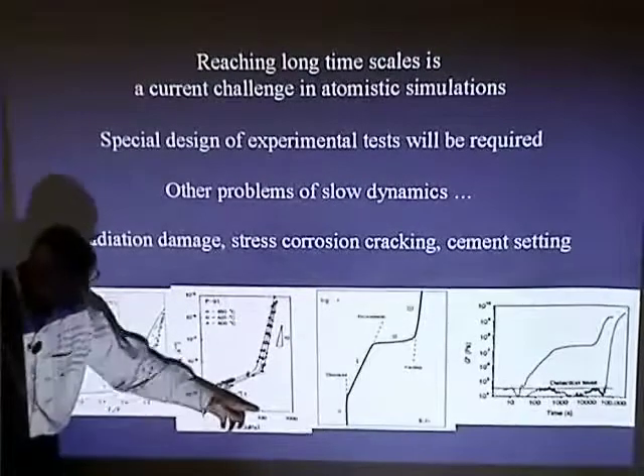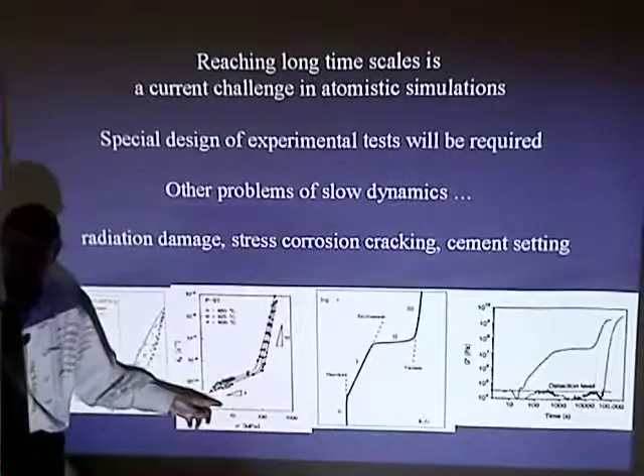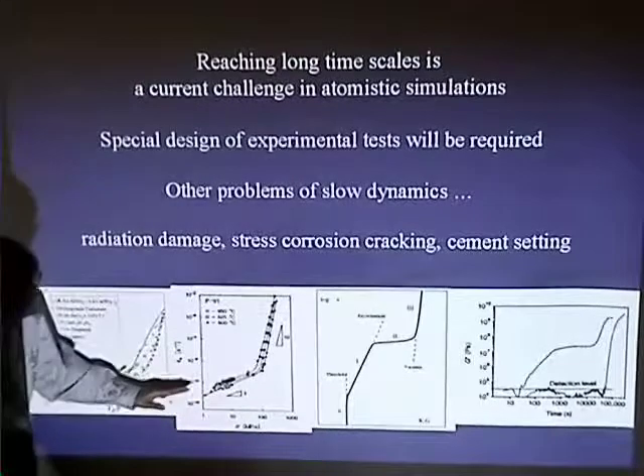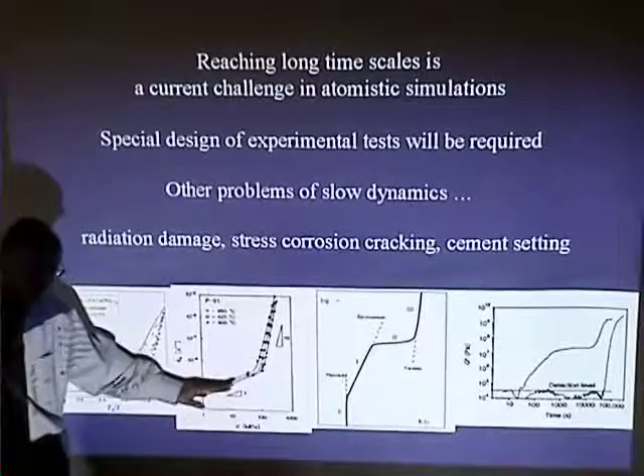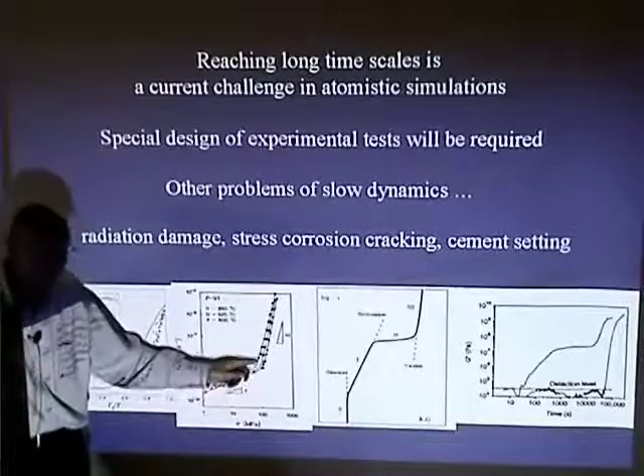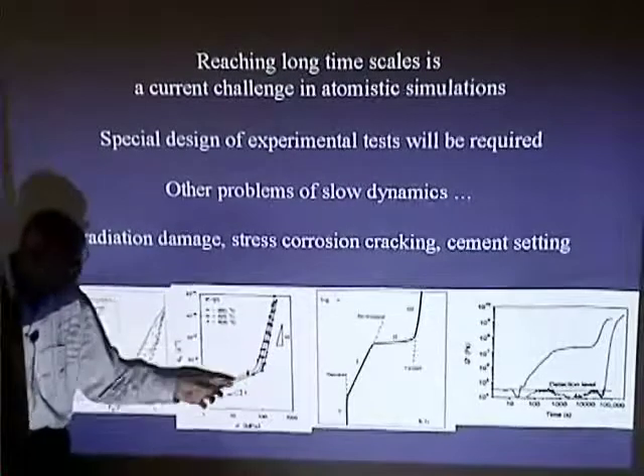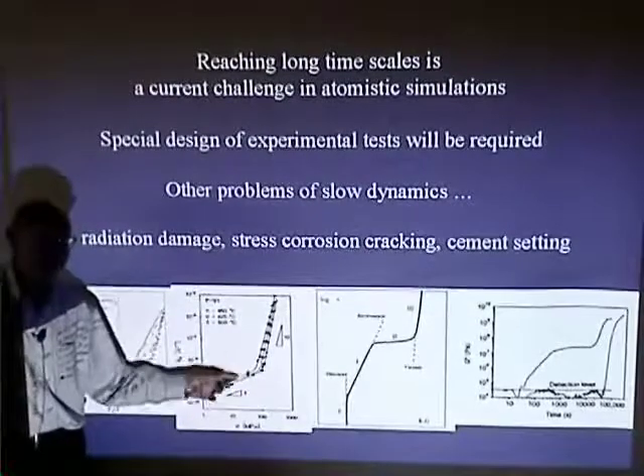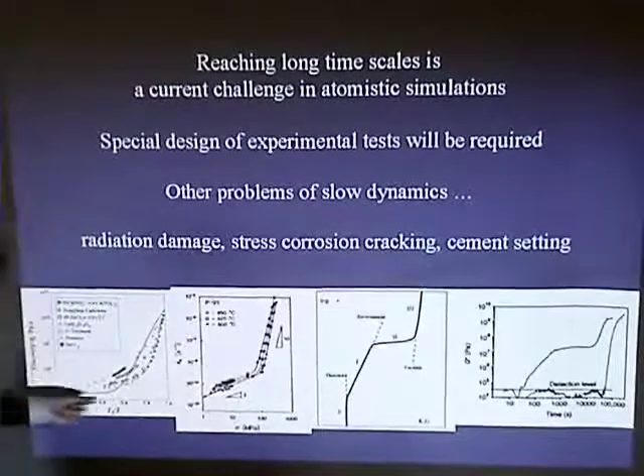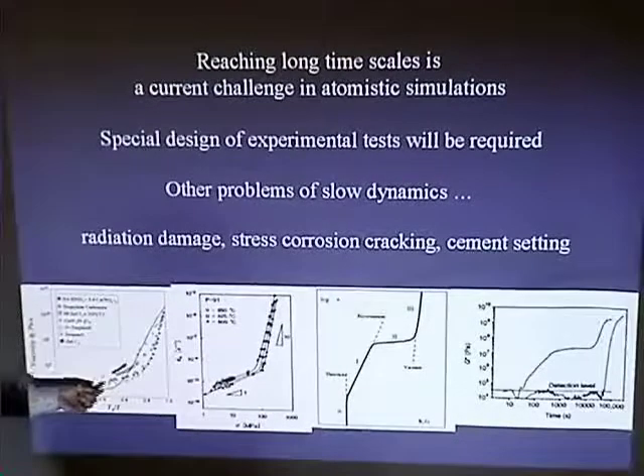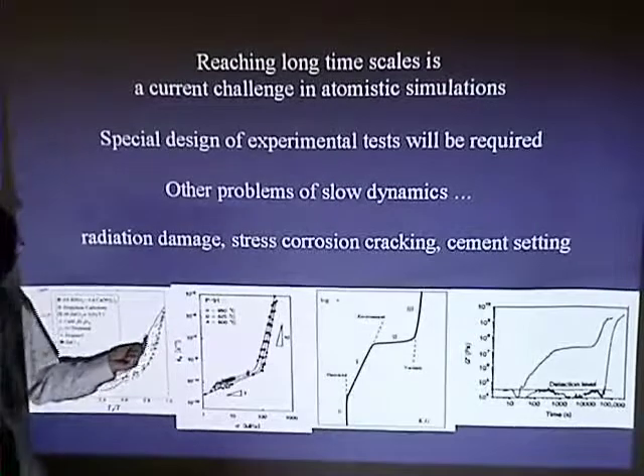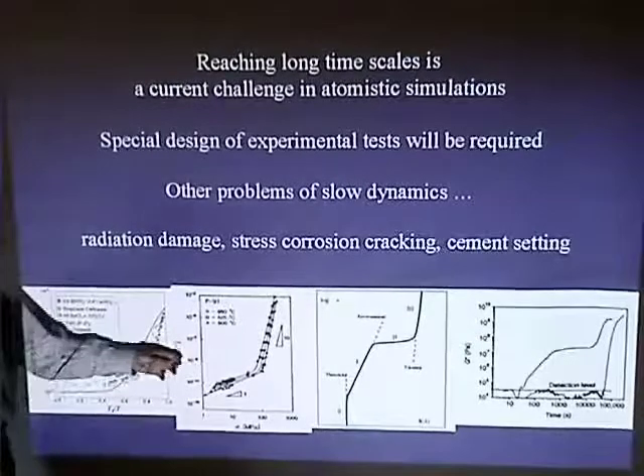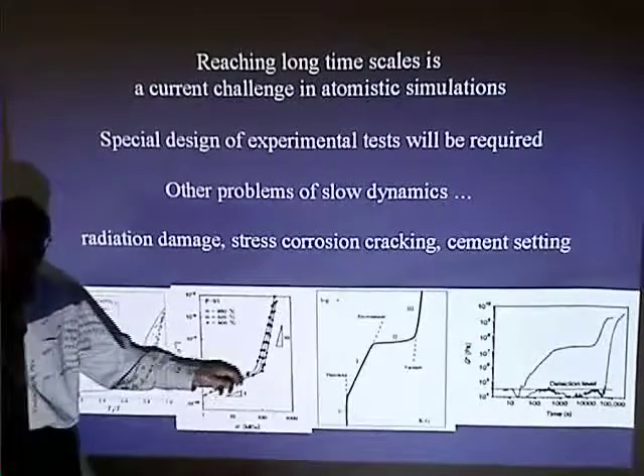In this case, the state variable is the stress. You see there's a plateau, a gradual increase, and all of a sudden the onset. So this will be our high temperature viscosity, exactly this. As you lower the temperature, at some point the viscosity shoots up. And here, at some point, the strain rate starts to shoot up.